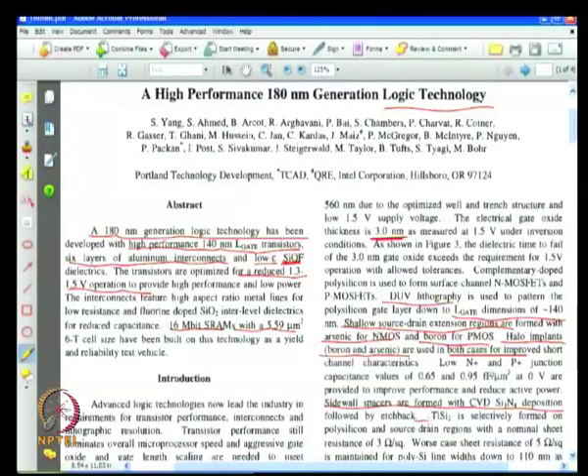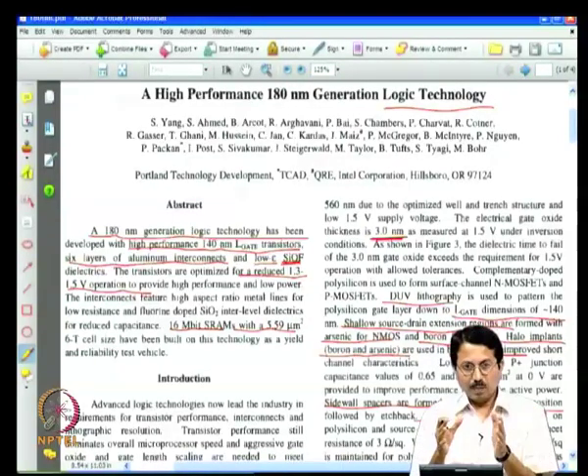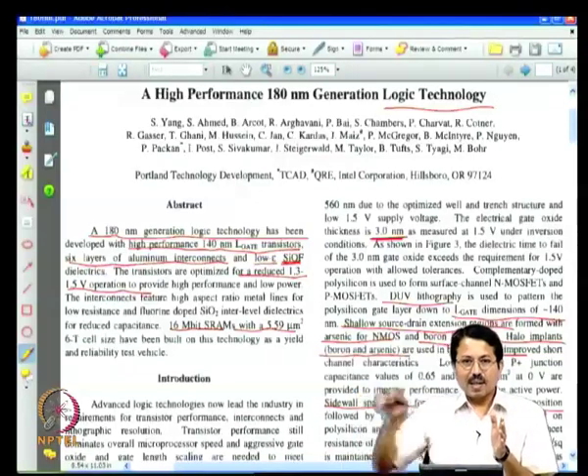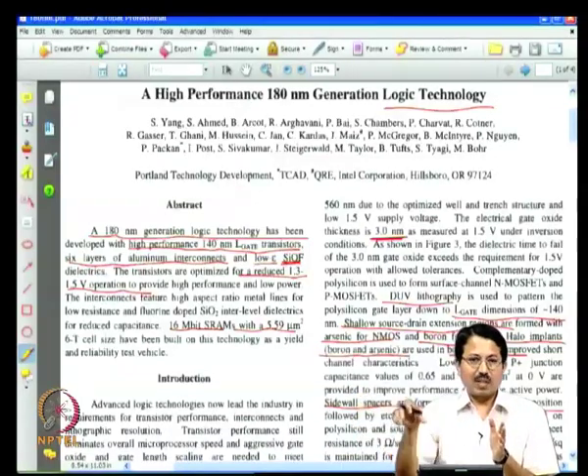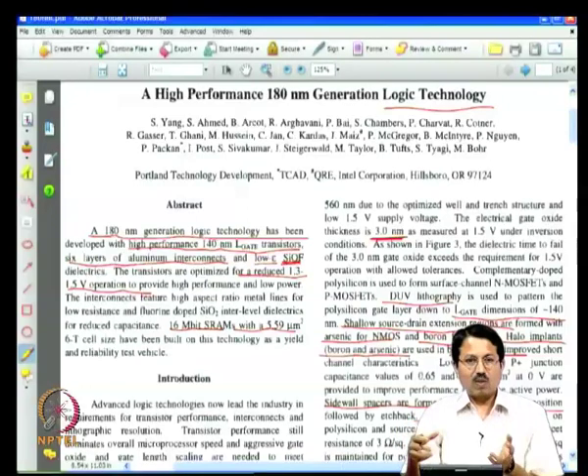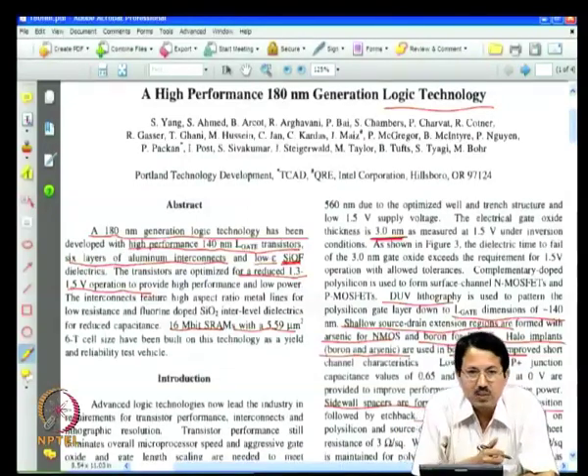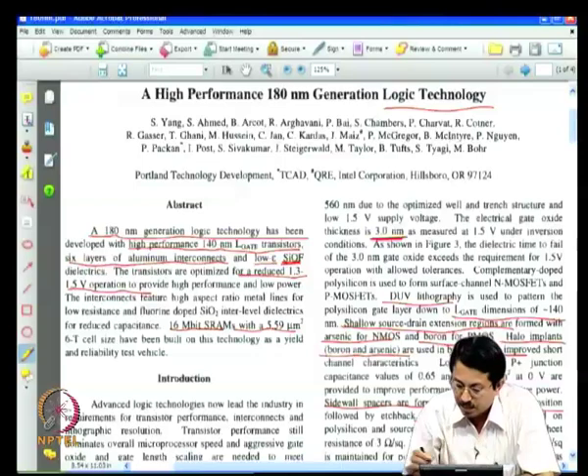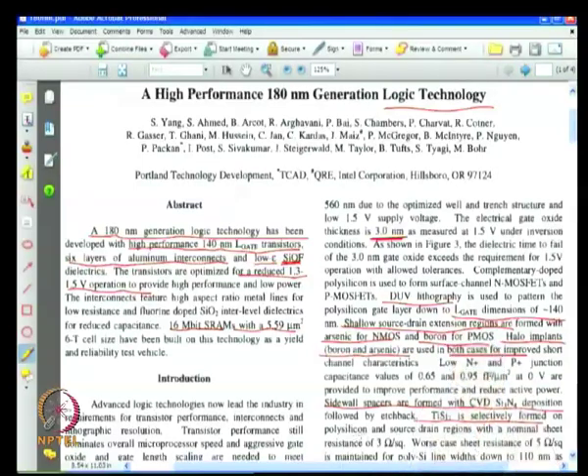They use silicide, titanium silicide. Remember the parasitic region that we talked about, after the gating of the transistor there is a contact and in between there is silicon, and if you convert it into a silicide you get lower resistivity. In this technology they are using titanium silicide, so that the typical sheet resistance on poly and source drain regions is 3 ohm per square. That is the kind of sheet resistance that you can get, which is a very low sheet resistance by the way.